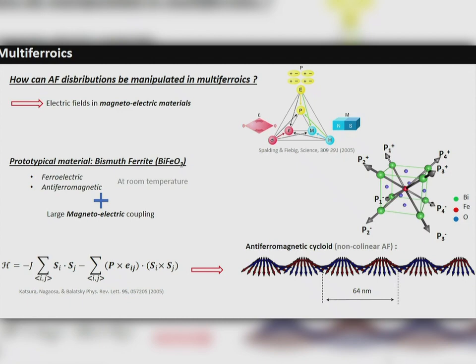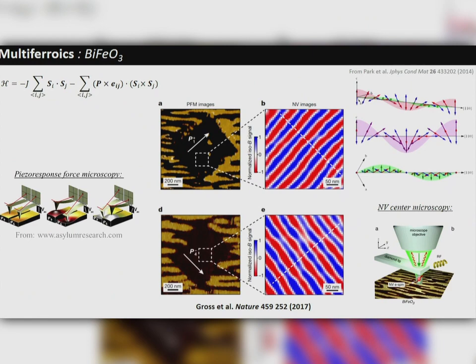But the nice thing about that material is that, as I said, the antiferromagnetic order is somehow coupled to the ferroic order, and you can see that, for example, in an experiment we did. So here it's a piezoresponse force microscope. Basically what you see here is the image of the ferroelectric order. And then we write a square where we have only one polarization, and here it is the NV center image.